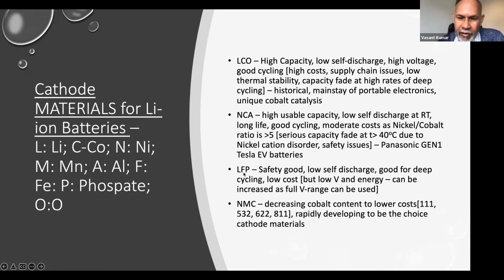For safety, lithium iron phosphate is the best. It doesn't use any cobalt, so potentially it's made of materials which are readily available. It is relatively low cost. It's got a very low self-discharge. It can be cycled many, many times. It has got low potential. As a result of that, the theoretical energy is lower than all the other lithium batteries that we're talking about. However, it can use the full potential range available. So if that point is taken into account, it's actually surprisingly good. Therefore, it's not surprising there are lots of cars available with LFP at the moment.